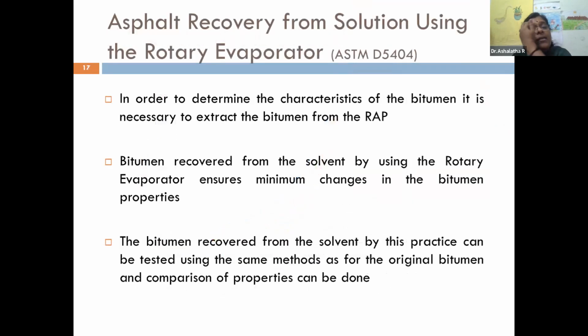Okay. And rotary evaporator, we use the rotary evaporator because we needed to understand the characteristics of the bitumen. So for that, we wanted to extract the bitumen from the RAP, and the bitumen is recovered from the solvent by using this rotary evaporator. That ensures that there's minimum change in the bitumen property. So we adopted that. And the bitumen recovered from the solvent by this practice can be tested using the same method as for the original bitumen, and the comparison of properties can be done.